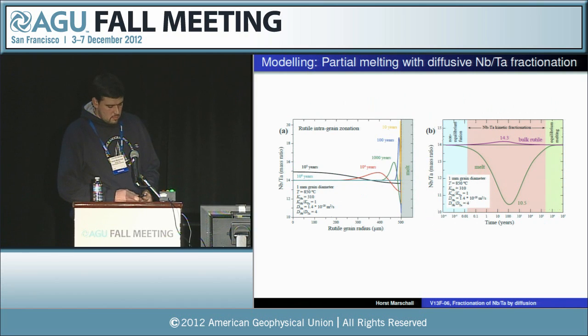So this is depicting the thing in detail. Here's the melt, here's the rutile crystal, this is the radius of the rutile crystal, niobium-tantalum ratio. You're starting at 14, the bulk silicate earth value, and at very short time scales, there's a yellow line, a very steep profile, and with time you get longer and longer profile length, and at about 1 million years the whole thing is equilibrated.